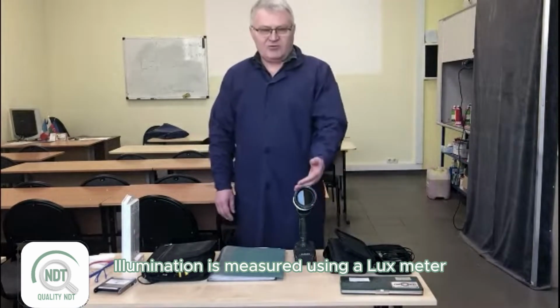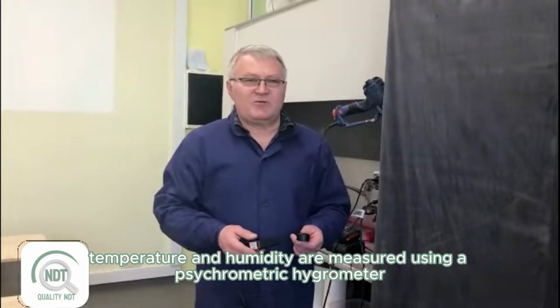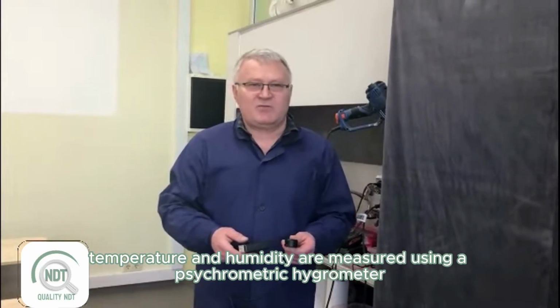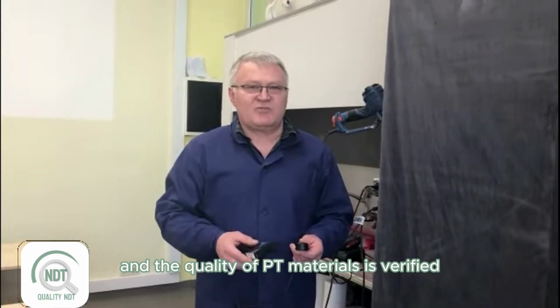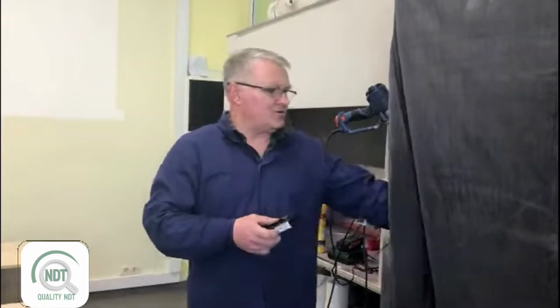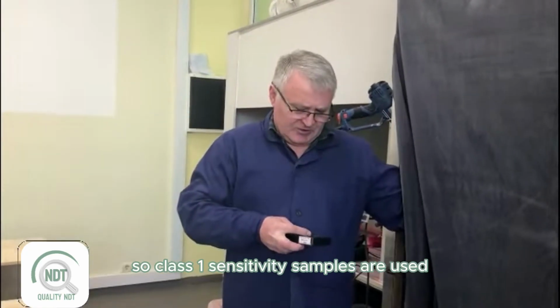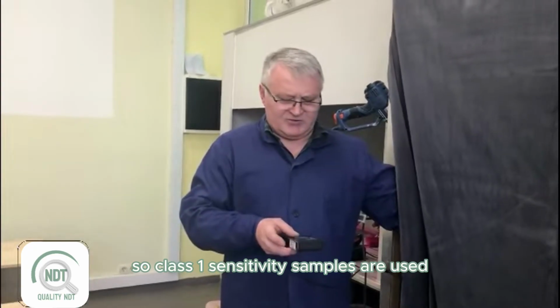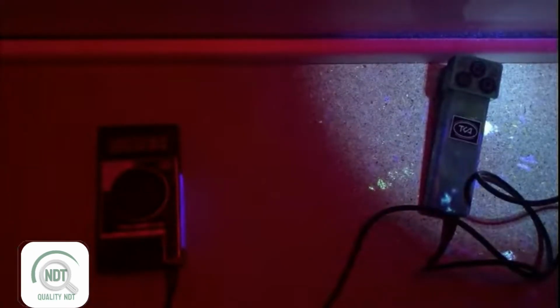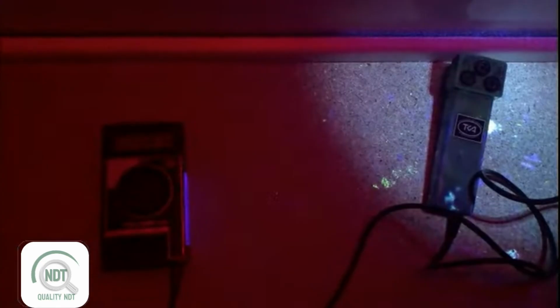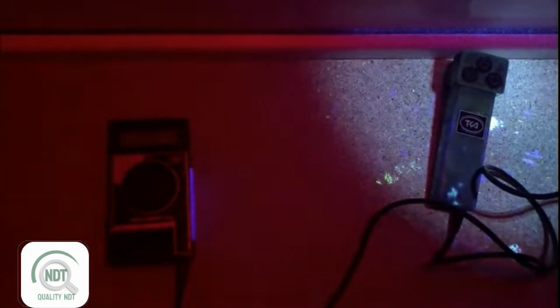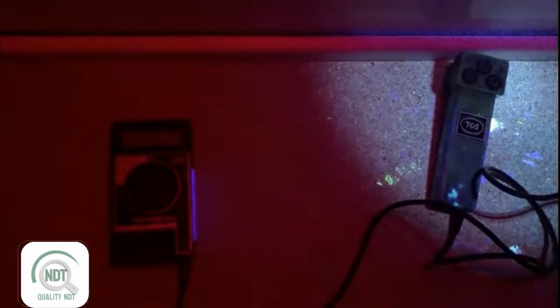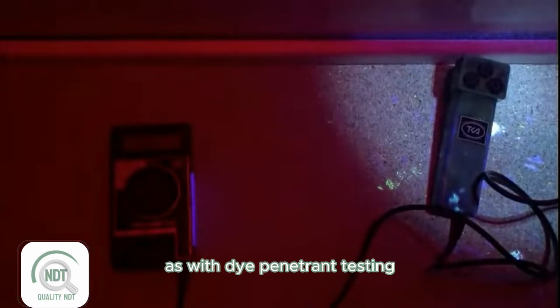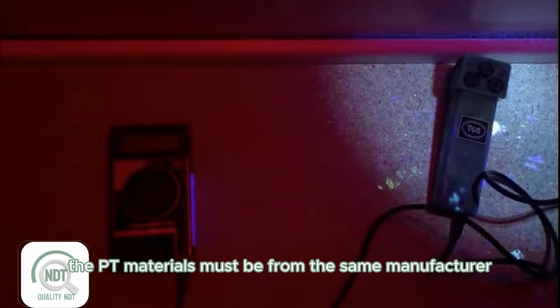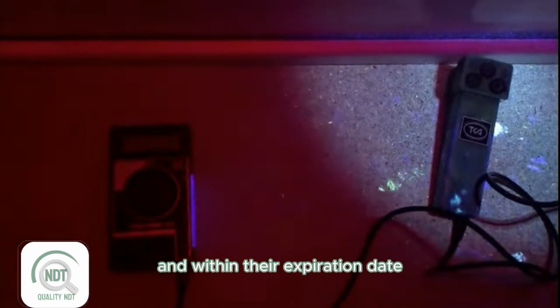Illumination is measured using a lux meter, temperature and humidity are measured using a psychrometric hygrometer, and the quality of PT materials is verified using a sensitivity sample. The luminescent method is more sensitive, so Class 1 sensitivity samples are used. As with dye penetrant testing, the PT materials must be from the same manufacturer and within their expiration date.